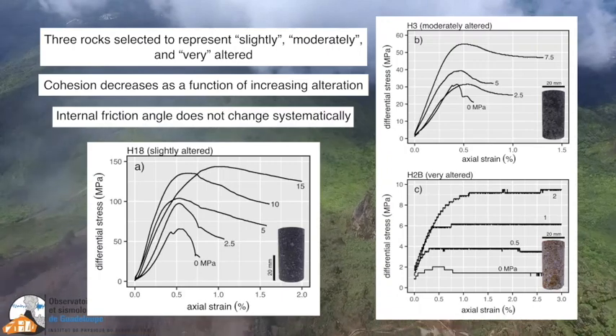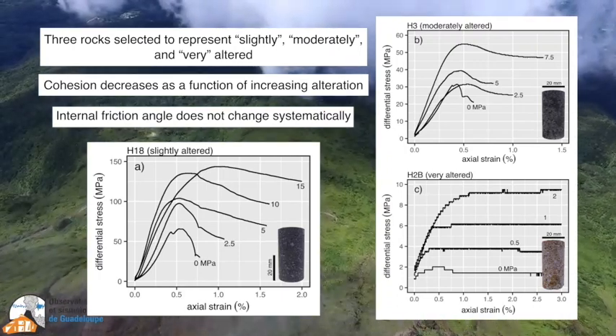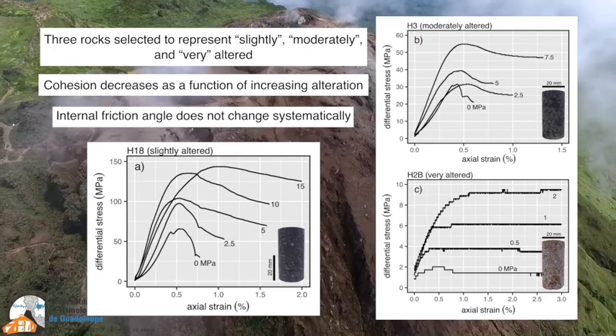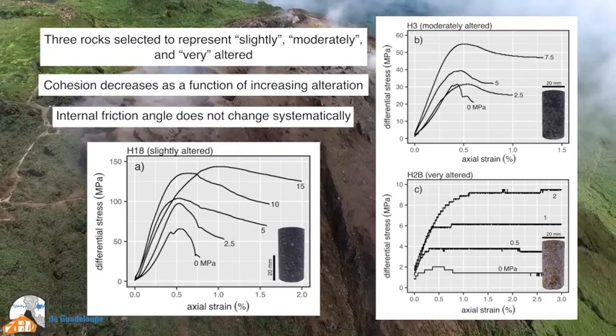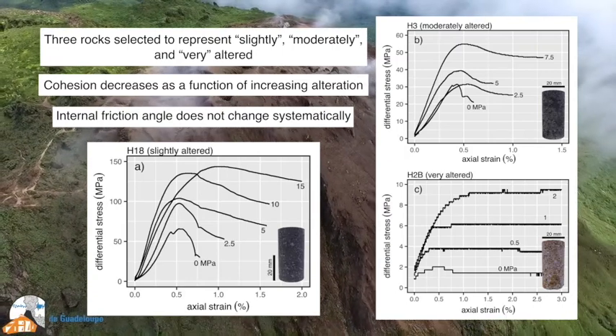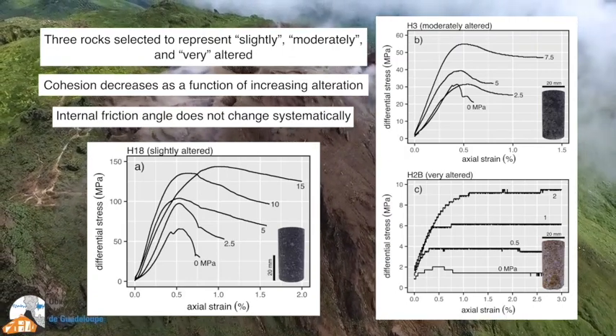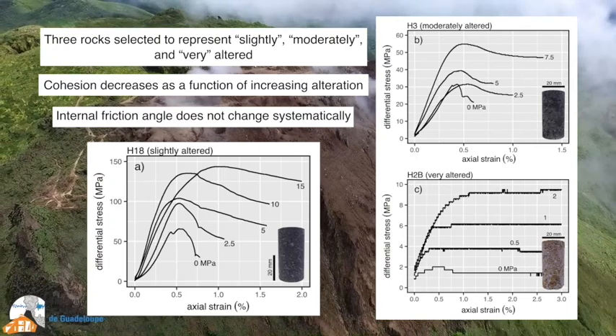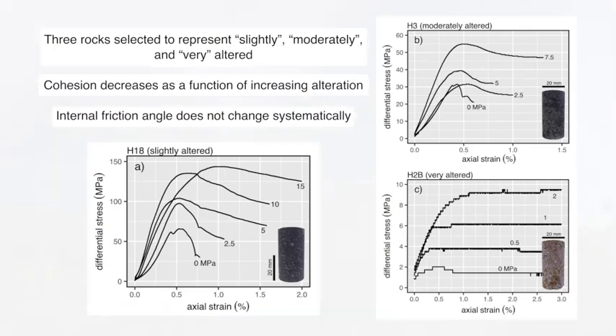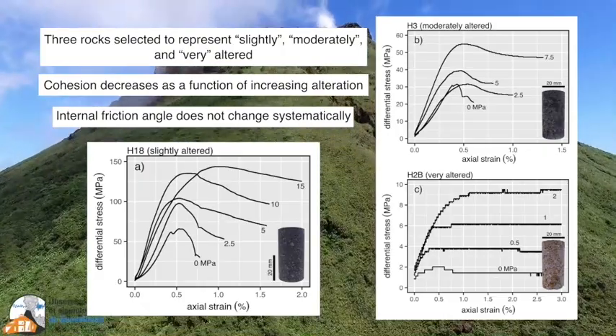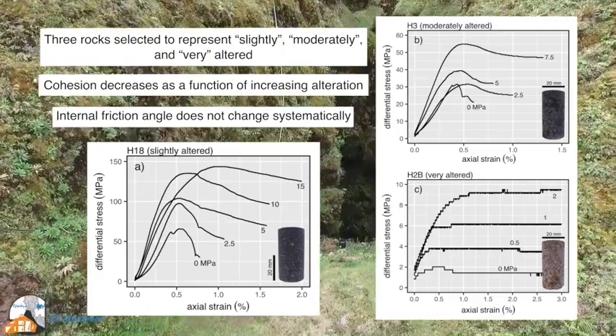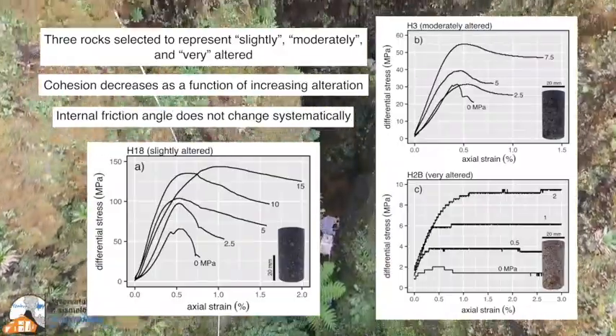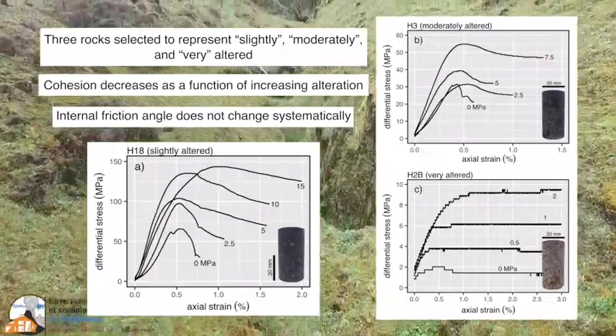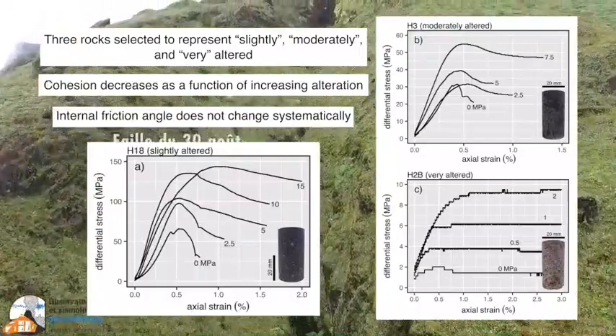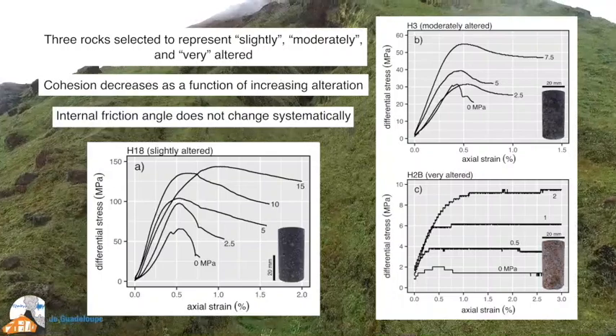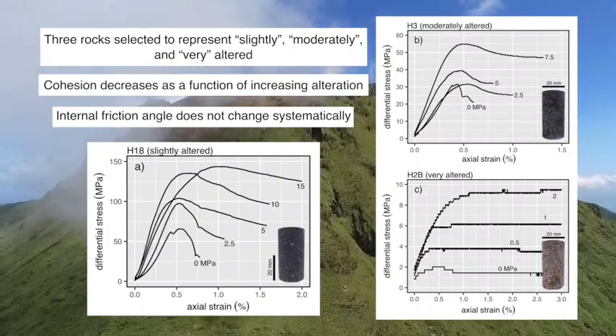Triaxial deformation experiments were only performed on 3 blocks, chosen to represent slightly, moderately, and very altered rocks at La Soufrière de Guadeloupe. The graphs provided here show stress-strain curves for samples of each block deformed under different effective pressures, indicated by the number next to each curve. Experiments at different effective pressures were required to calculate cohesion and the internal angle of friction, parameters required in our large-scale flank stability modeling. We find that increasing alteration reduces cohesion but does not systematically influence the internal friction angle.